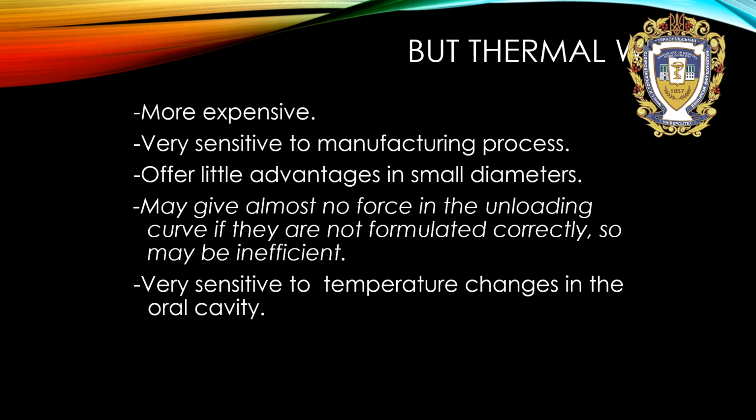But disadvantages of thermal wires: they are more expensive, very sensitive to the manufacturing process, offer little advantage in small diameters, may give almost no force in the unloading curve if they are not formulated correctly, so may be inefficient, and are very sensitive to temperature changes in the oral cavity.